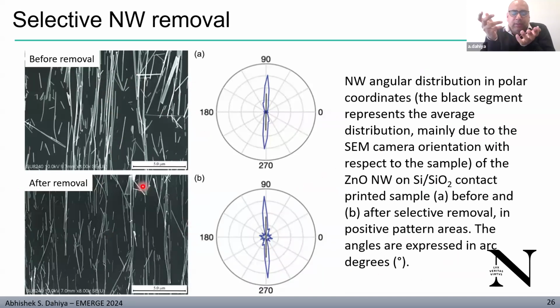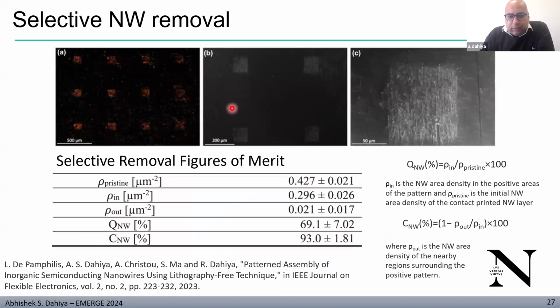With PDMS, for example, it's expected that the nanowire direction could be disturbed while removing these wires, but from the figure here, we have confirmed that it remained more or less aligned in the same manner. We have also calculated some other figures of merit, for instance, the density of wires in the positive area. Positive area is defined where the nanowires should remain, which is around 69%. And we have another figure of merit, comparing how much the wires have been removed from the outside and inside area, which is around 93%.